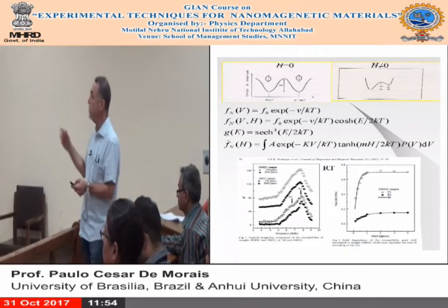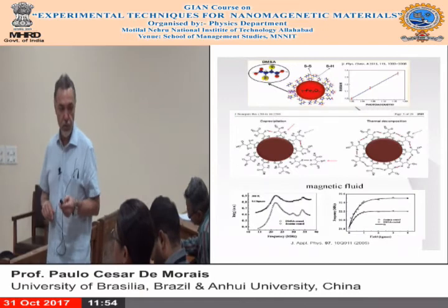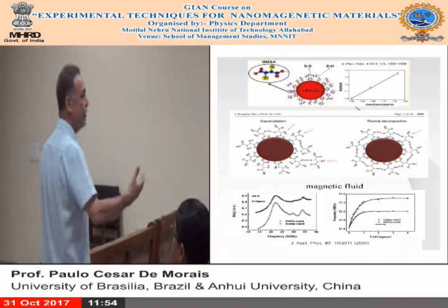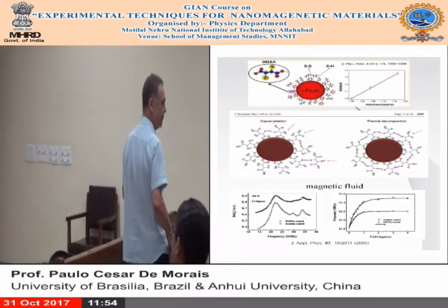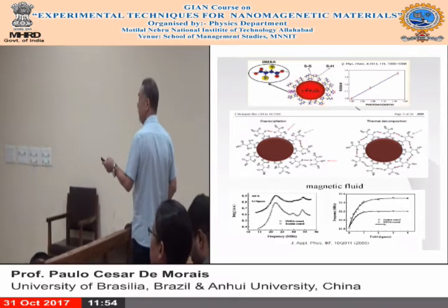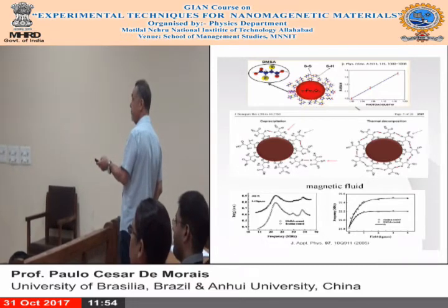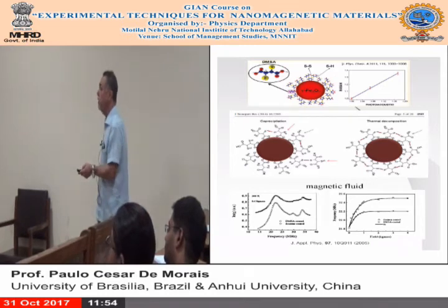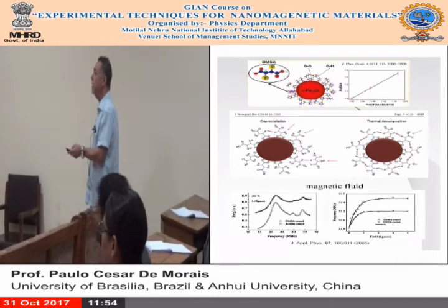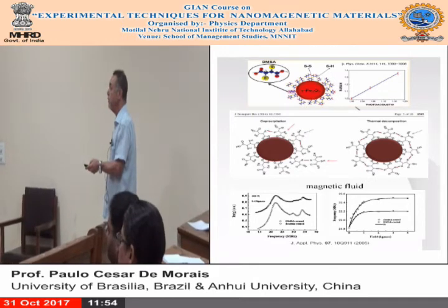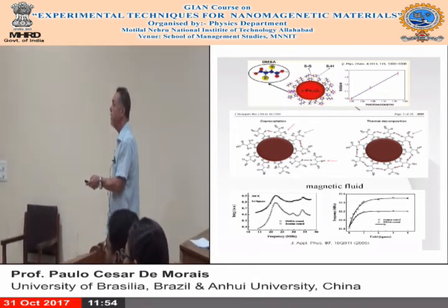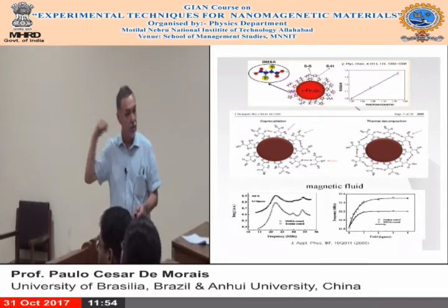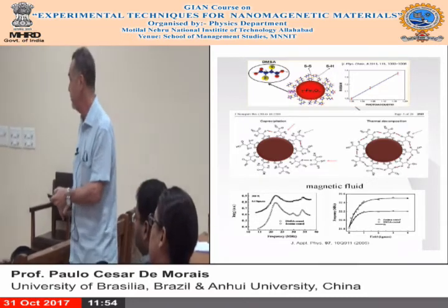OK, this is another system we produced there. So nanoparticles that are surface decorated with different molecules. We also take the measurement we call dynamical susceptibility, and measure the imaginary component as a function of frequency, extract the peak positions, and measure as a function of field. So we use the same model as the last slide to fit this data.